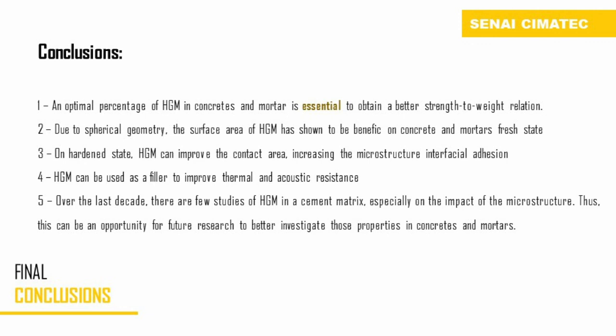Now, after our results were shown, it can be concluded that an optimal percentage of HGM in concrete and mortar is essential to obtain a better strength-to-weight relation. Due to the spherical geometry, the surface area of HGM is shown to be beneficial to the fresh state of concrete and mortar. In the hardened state, HGM can improve the contact area, increasing the microstructure interfacial adhesion. HGM can be used as a filler to improve thermal and acoustic resistance.